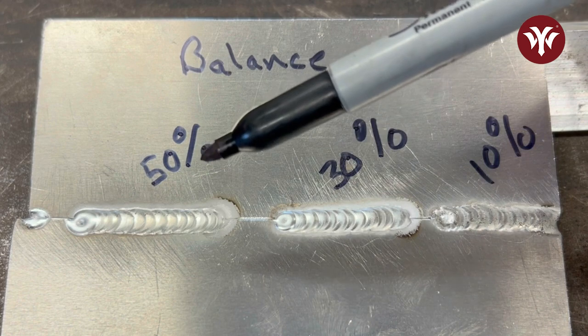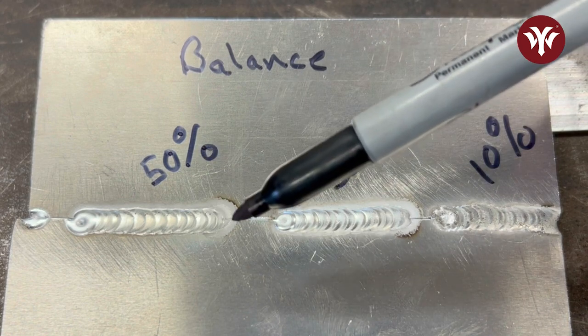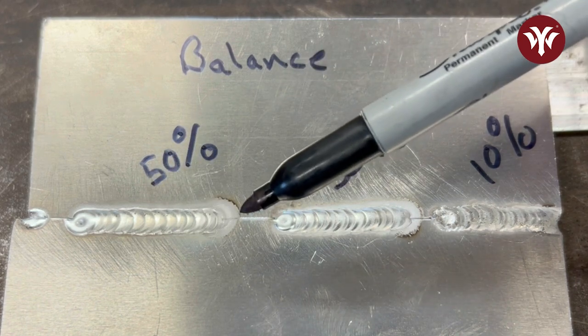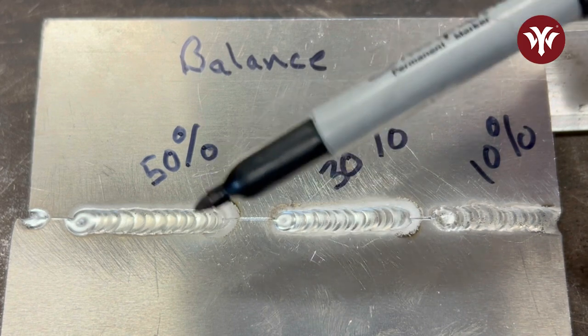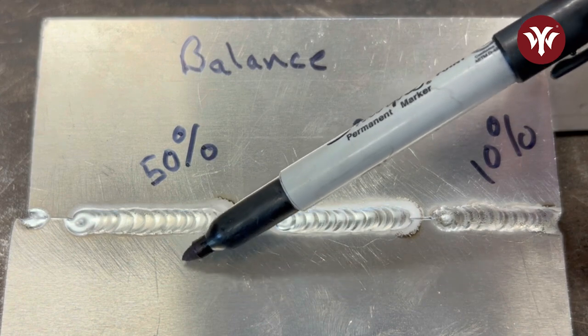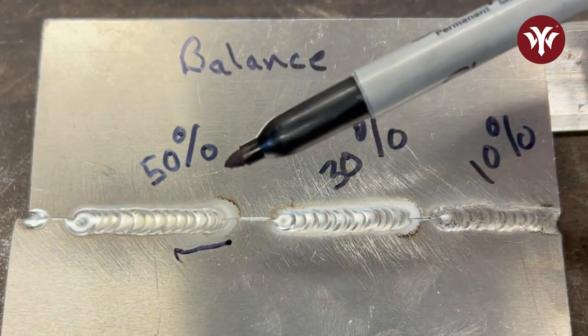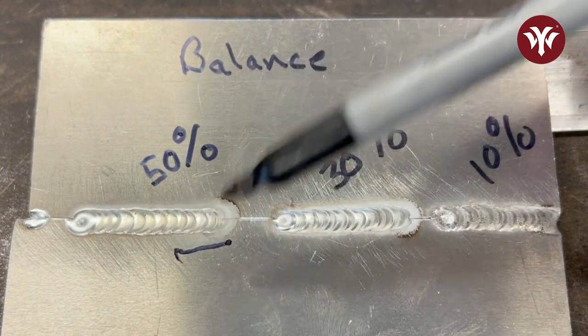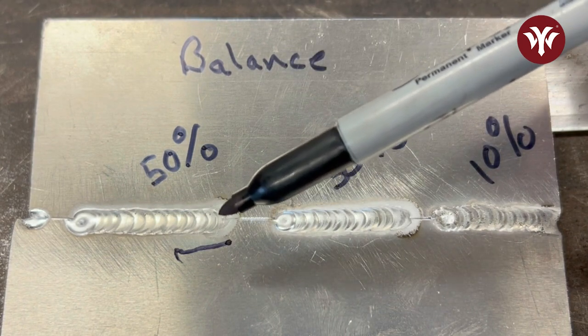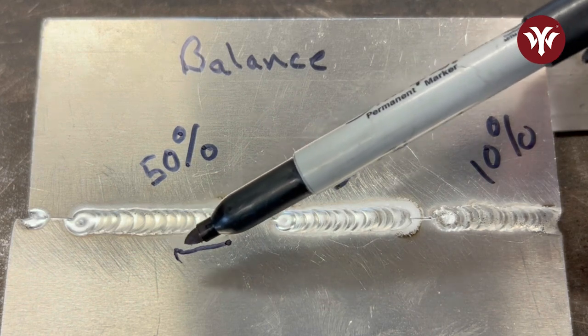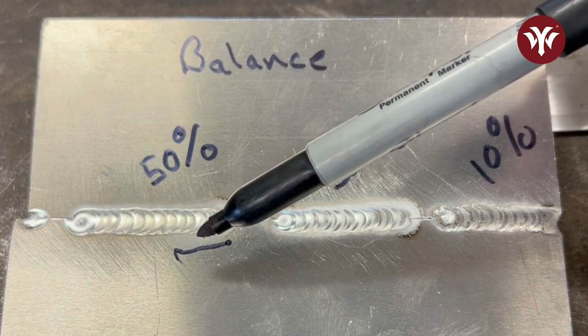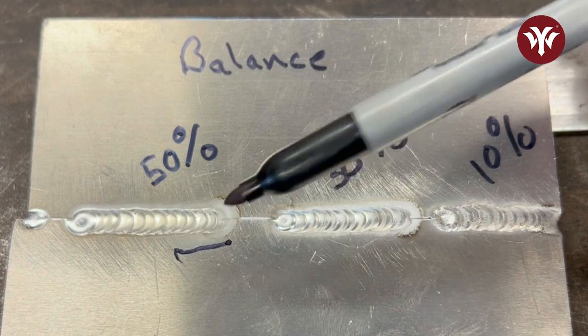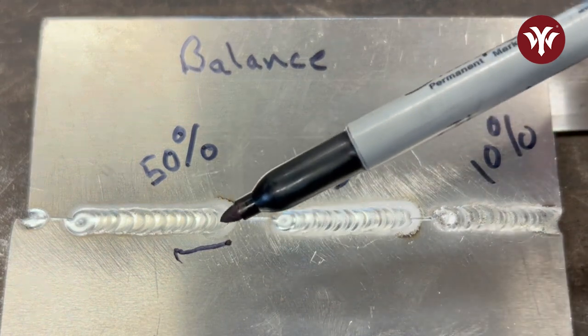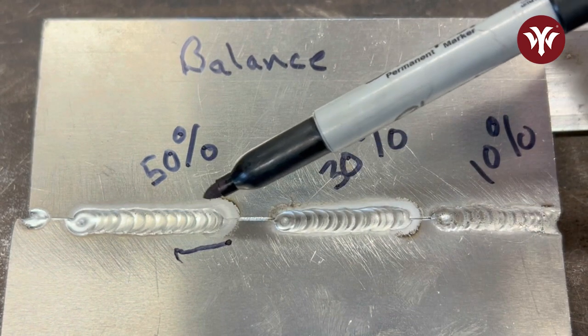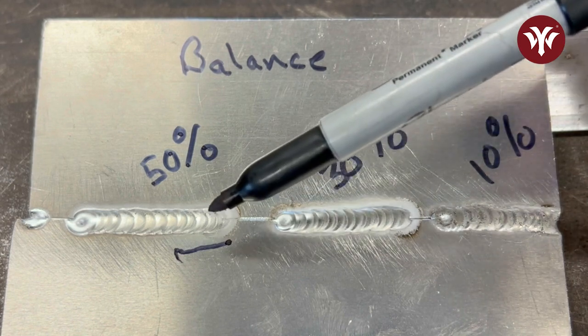Now here is 50%, and the balance does go higher than that. The actual effective cleaning zone didn't get much larger, so I think we were probably maxed out to the shielding gas coverage we had. If you wanted this etching to come out even farther, like out to here, which there's not really a big reason to, the cleaning action will only take place inside of the argon shielding gas. So I probably didn't have much gas coming down over here because of the size of the nozzle I was using. So that just shows you how nozzle size does play a role in cleaning action. But effectively, between weld to weld, there isn't a lot of difference.